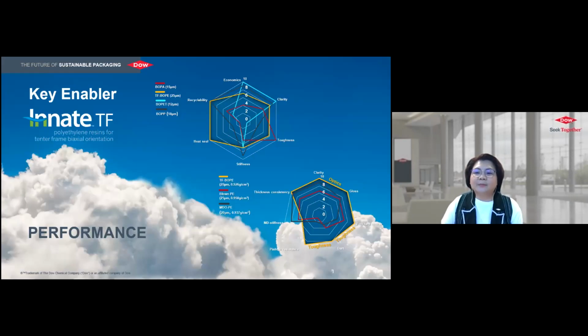So tenter frame polyethylene is relatively new to the market. Let me elaborate a little bit more about the technology. It's actually made with a tenter frame biaxial oriented process, similar to a BOPP line. In the process, polyethylene is firstly extruded from a cast flat die. Then it is stretched in machine direction by about 4 to 5 times, followed by about 8 to 9 times stretching in the transverse direction.